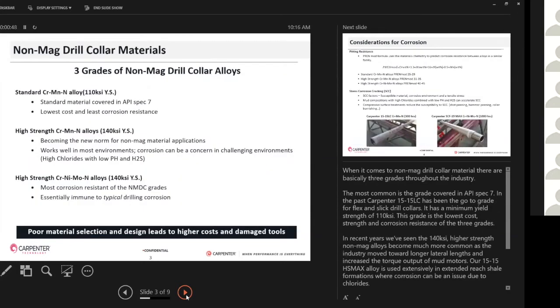So when it comes to non-mag drill collars, there's basically three grades throughout the industry. The most common grade is covered in API Spec 7. In the past, our 1515 LC, which is that standard grade, has been the go-to grade for flex and slick collars. It has minimum yield strength of 110 KSI. This is the lowest grade, lowest cost, lowest strength, and has the least corrosion resistance of these three grades.